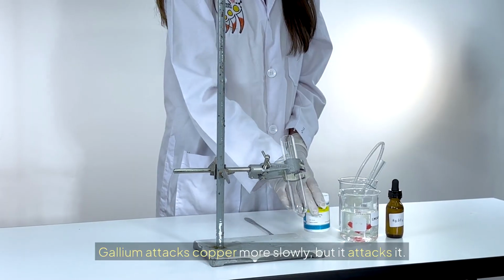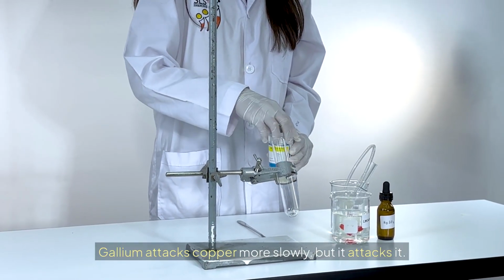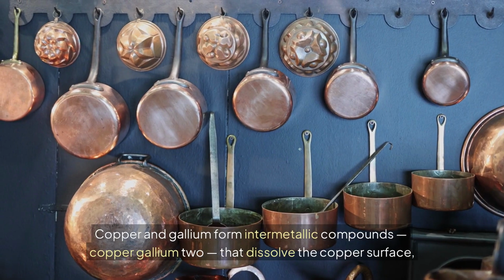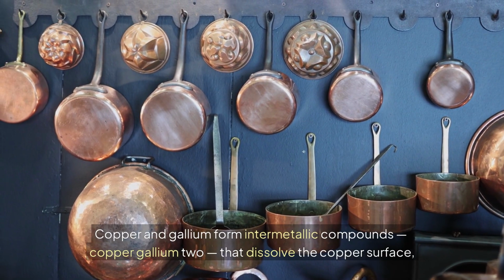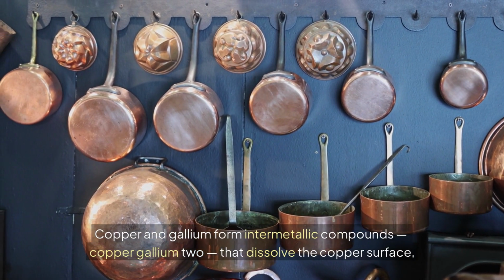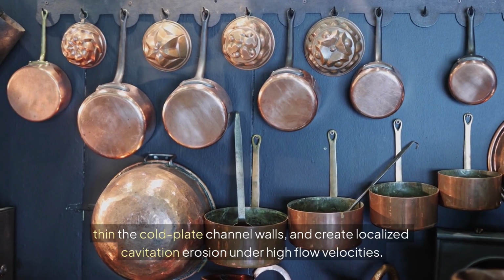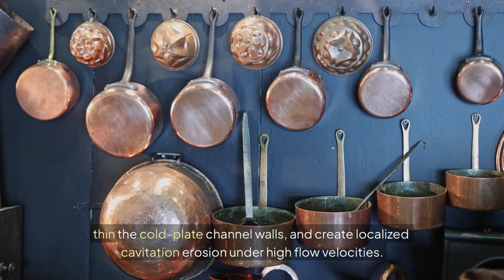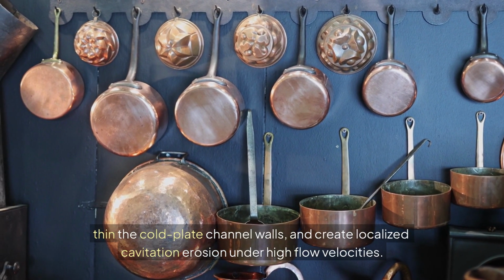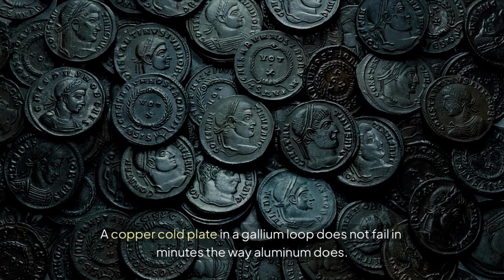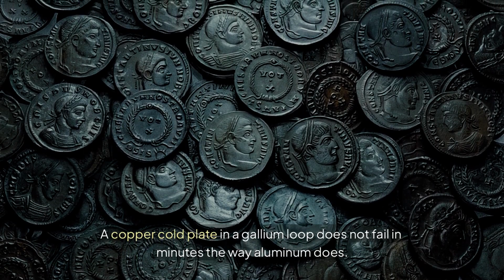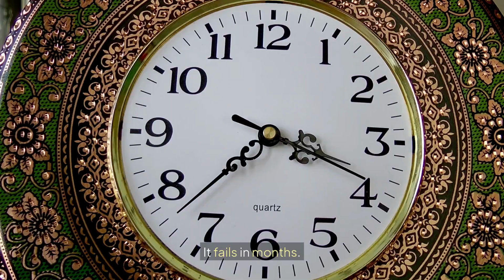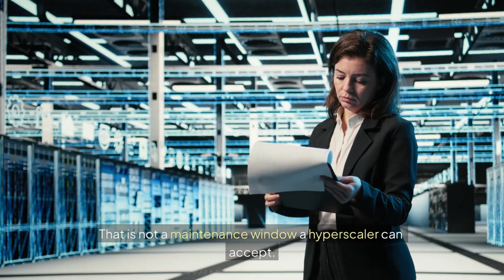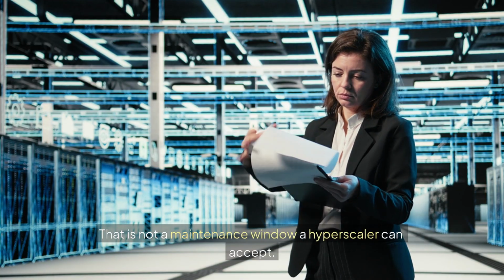Gallium attacks copper more slowly, but it attacks it. Copper and gallium form intermetallic compounds, CuGa2, that dissolve the copper surface, thin the cold plate channel walls, and create localized cavitation erosion under high flow velocities. A copper cold plate in a gallium loop does not fail in minutes the way aluminum does. It fails in months. That is not a maintenance window a hyperscaler can accept.